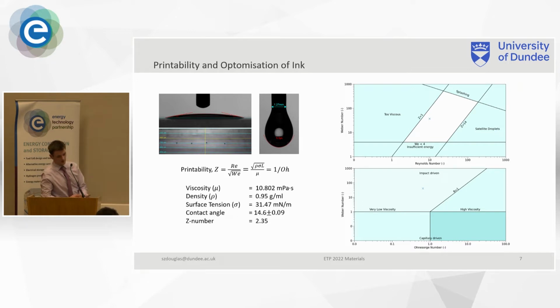So we've got two on the left there, and the right we've got the sort of limits that we want. So the Z is the printability, it's another dimensionless number. We want to be between 1 and 14, which we measure with that equation. That X is where our ink is, so it's in the printable region. The top and bottom regions, the limits, can be controlled by its velocity. So if the nozzle voltage is insufficient, then it won't jet. You won't get a droplet. If it's too fast, the voltage is too high, there'll be too much force as the droplet hits the deposit, and it'll splash, and you'll get deforms.